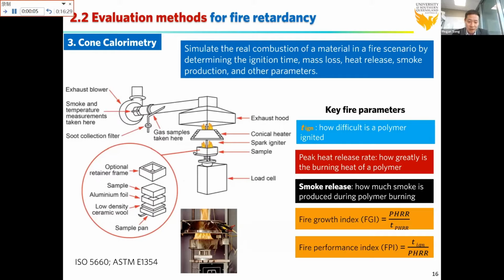This is more powerful. This picture just shows the fire testing. Generally, you expose your sample to a conical heater, and you also use a spark igniter. By doing this, we can simulate the real combustion of material in a real fire scenario by determining the ignition time, mass loss, heat release, and smoke production, and other key fire parameters. So this is a really powerful fire testing facility for fire retardant materials.